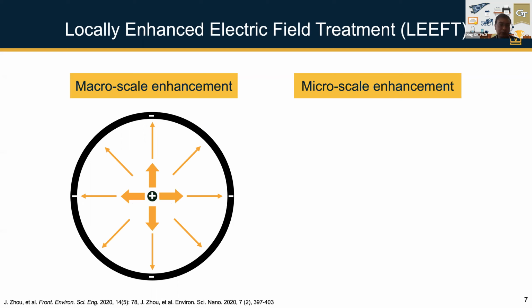Based on the theory of electric field distribution, we can calculate that the electric field strength near the center electrode is much stronger than in the outer space. The electric field strength is inversely proportional to the distance from the point to the center of the tube. So that means the electric field strength near the center electrode will be much stronger. It really depends on the ratio of the diameters of the center electrode and the outer electrode, and also the distance from the center electrode. The electric field strength can easily be enhanced at least 20 to 30 times, so about a couple of tens of times of enhancement.